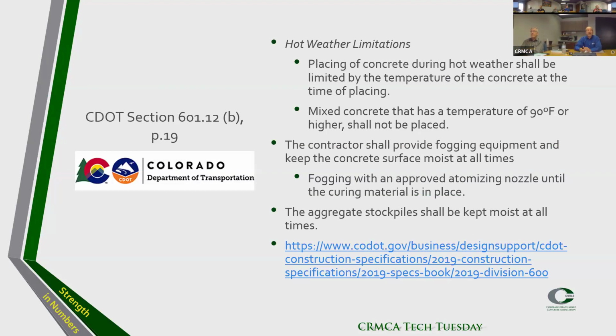This is from CDOT, directly from their website. The web link is underneath. It says hot weather limitations. I'm just going to read it. Placing of concrete during hot weather shall be limited by the temperature of the concrete at the time of placing. Mixed concrete that has a temperature of 90 or higher shall not be placed. Contractor shall provide fogging equipment and keep the concrete surface moist at all times, fogging with an approved atomizing nozzle until the curing material is in place. And the aggregate stockpile shall be kept moist at all times. Again, that's directly taken from the CDOT spec. You can look it up, 601.12(b) on page 19. So again, CDOT limits temperature to 90 degrees at all times.